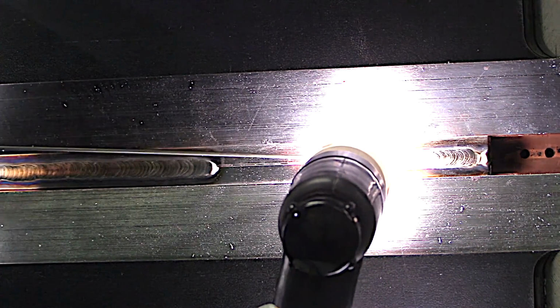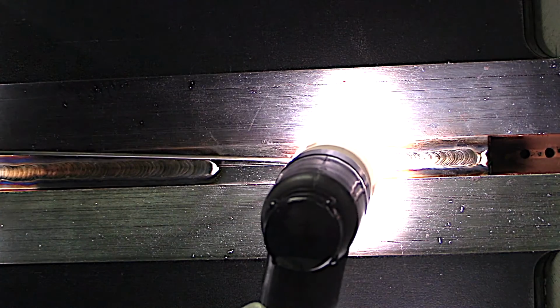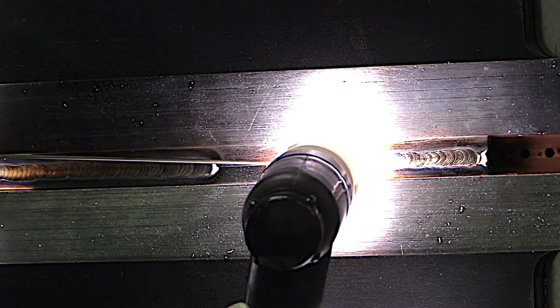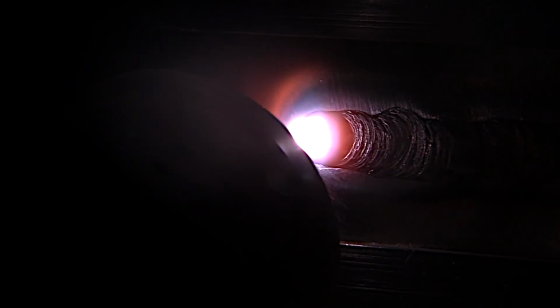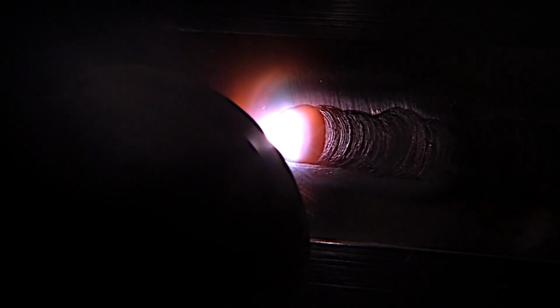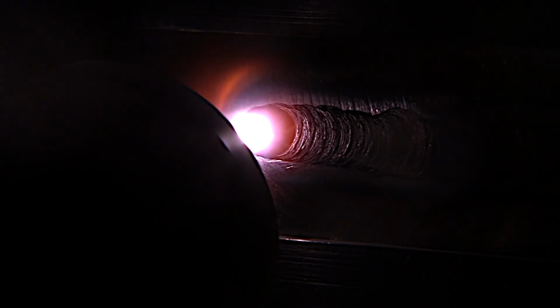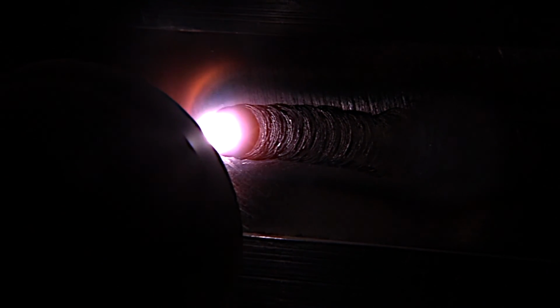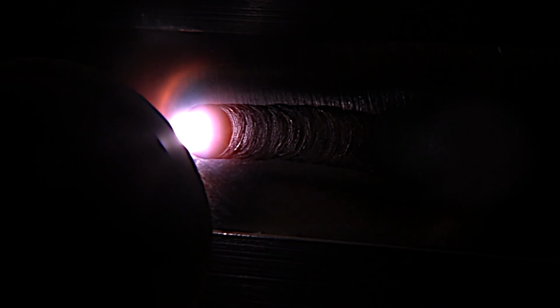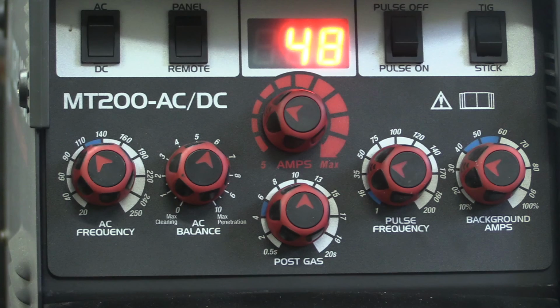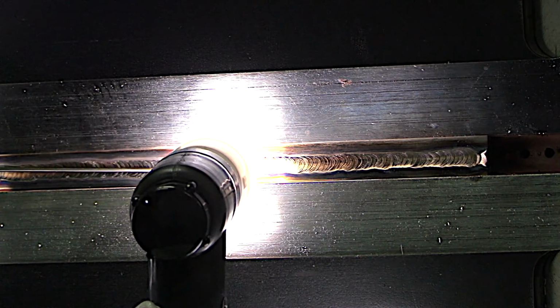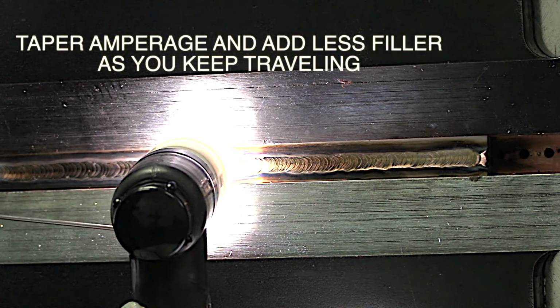One of the main skills in taking any test should be to not leave a crater crack when you have to terminate a weld. So this is the way we did the test. We required starting in the middle and then welding into the middle and tapering off without leaving any kind of crater crack or any kind of problem that would show up in X-ray. Oftentimes in aerospace repairs, you're never welding more than a couple of inches anyway.